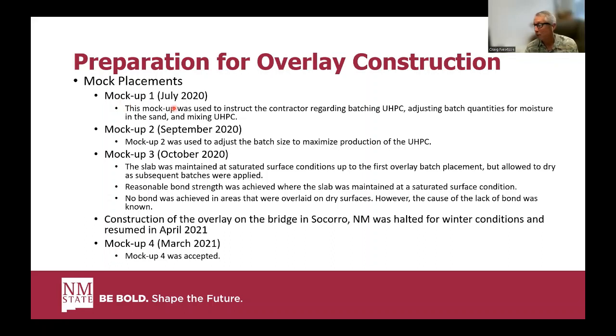So we had specified dry sand. The contractor didn't adjust for the moisture that was in the sand at the batch plant. So the mix was much more fluid than what it should have been. Basically, we had to work on adjusting the batch quantities, trying to get the contractor just dialed in on how to actually mix UHPC. Really long mixing times, stuff that typical contractors are not prepared for.